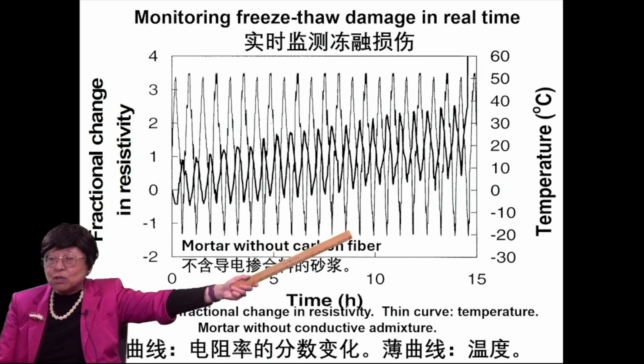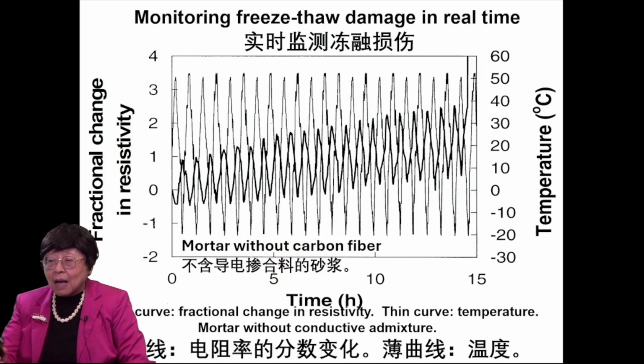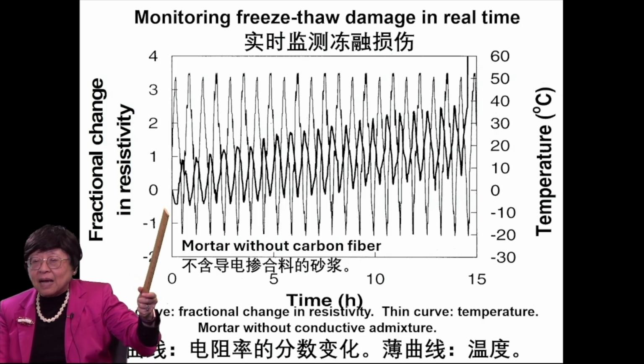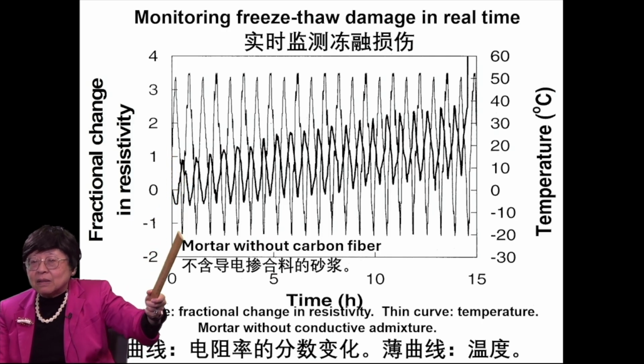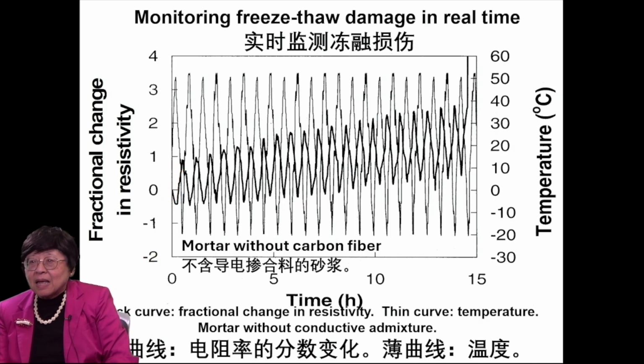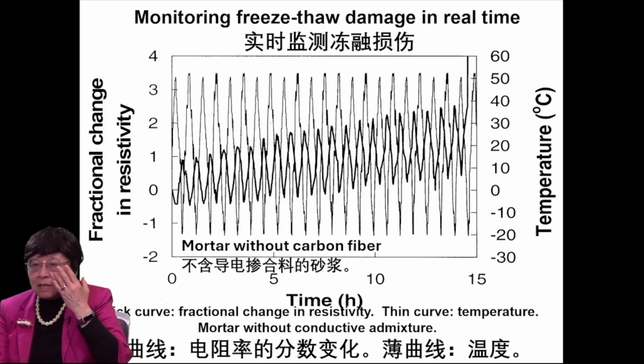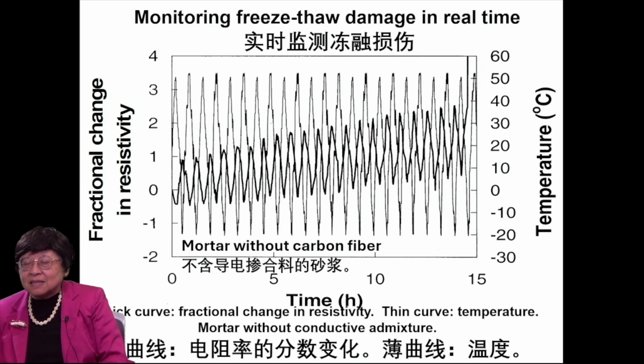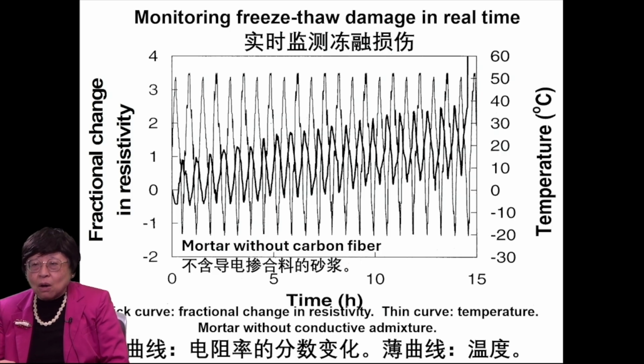Here in thin line is the temperature varying from below 0 C to above 0 C, and in thick line is the resistance or resistivity. Every time the temperature goes down, the resistance goes up. This is the volume resistance that's being measured. And this trend is like what I mentioned before. That is, when you decrease the temperature, there is less thermal energy for the electrons to overcome certain diffuse interfaces inside the cement. As a result, you would have higher resistivity.